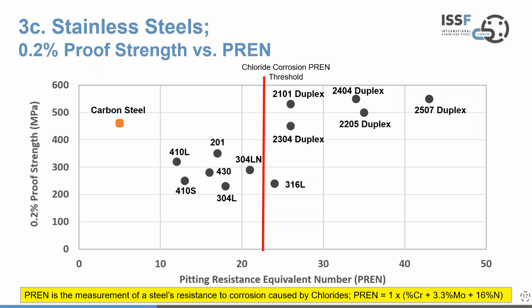Now, shown in the center of this chart are other stainless steels, and these have lower proof strength, but a fairly wide span of pitting resistance equivalent number, which means their corrosion resistance is somewhat variable. And you have in there a combination of martensitic grades to the left, ferritic and austenitics in the midsection, and then 316L more to the right. But these grades, when you're looking for high strength applications, are not the bunch of stainless steels you would normally look at first and foremost. It is the duplex family that are more interesting there.